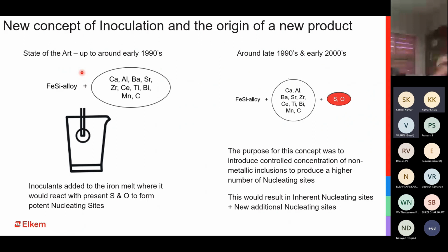We spoke about the basic ones. Now I'll talk to you about sulfur and oxygen, which I did say a few words about in the last slide. What was happening up to the early 1990s was that we had the ferrosilicon alloy and we were adding all these inoculating elements into that ferrosilicon alloy. And then when this inoculant was added into the melt, it would combine with the sulfur and oxygen present in the iron melt, and thereby form those potent nucleating sites on which the graphite growth would happen.